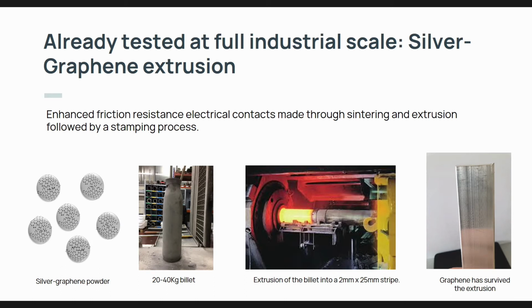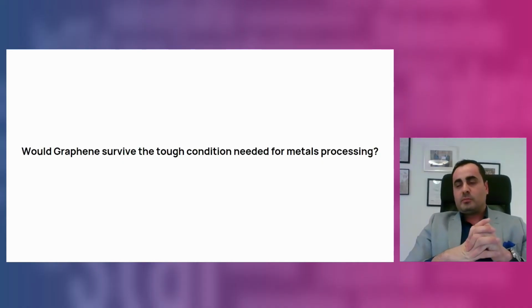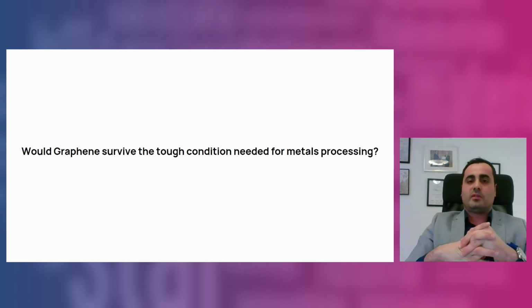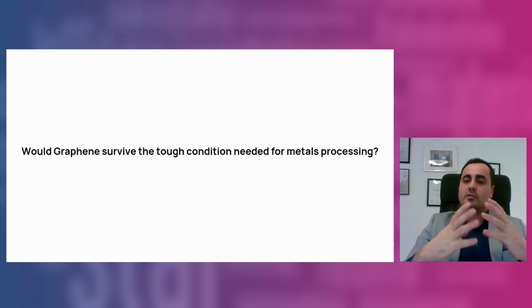As you can see here, you produce billets between 20 to 40 kilos. You do pre-sintering and you do the extrusion, and what you get at the end is like a stripe of the composite. So a common question we get from different industries: would graphene survive the tough conditions needed for processing